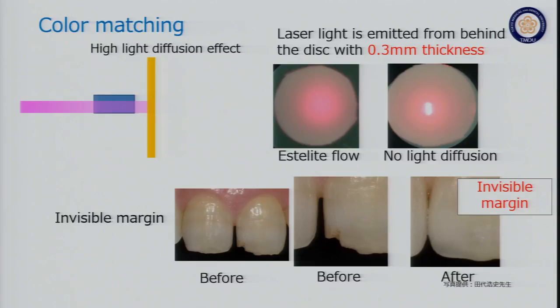There is a disc of the composite with this material. Another material does not have the appropriate light diffusion effect. And behind these discs, we apply the light. Then we can see the light like this. The shape of the light can be observed very clearly in the case of this kind of material. But when the material has a very appropriate light diffusion effect, the shape of the light becomes very unclear. Because of this kind of effect, the margin between the restoration and tooth becomes so unclear, an invisible margin.